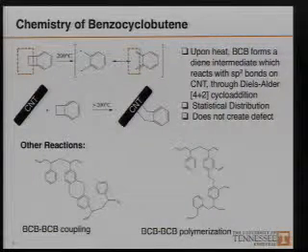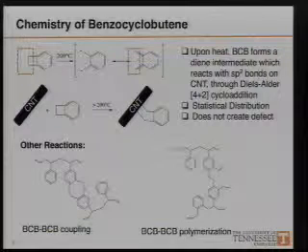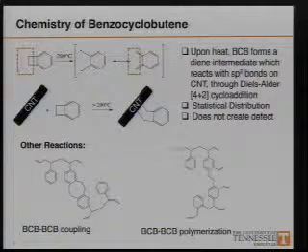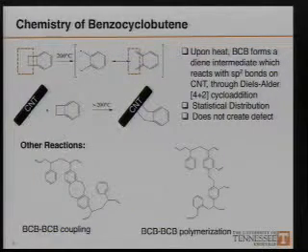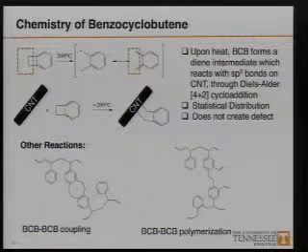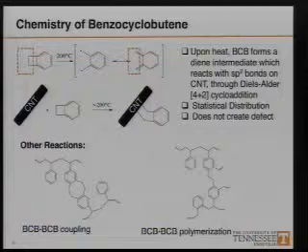And the advantage of this reaction is that it forms statistical distribution of functionalizations on the walls of nanotubes and does not create additional defects as oxidation does. Also, it does not require catalysts, and it does not release any small molecules during the reaction, like water, carboxylic acid, or CO2, whatever.